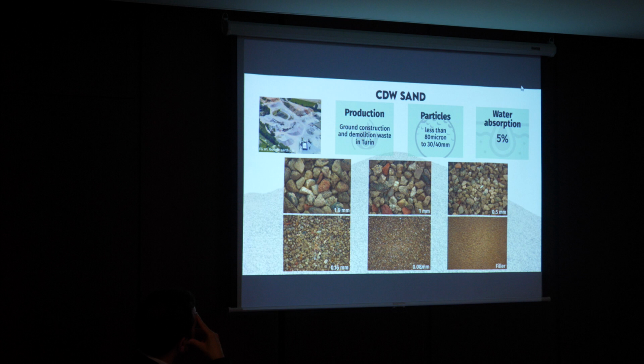In our case, we work with a construction and demolition waste sand that was produced in Italy, in Turin. It's a local product, composed of particles from less than 80 microns to around 30 and 40 millimeters. And this particular sand has a water absorption capacity of 5%. It's known that this property can affect the final properties of cementitious products like mortar or concrete. In our case, specifically, we work with this fraction only, the other fractions that are present in the standards and that are usually used for mortars, from 1.6 millimeters to the filler that is less than 80 microns.